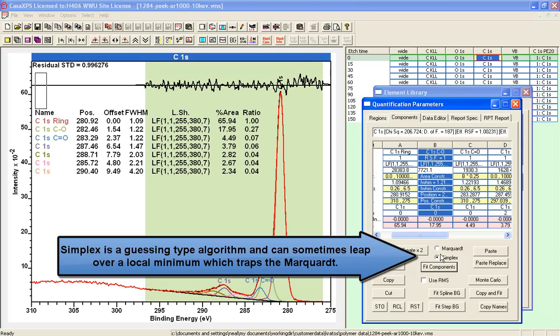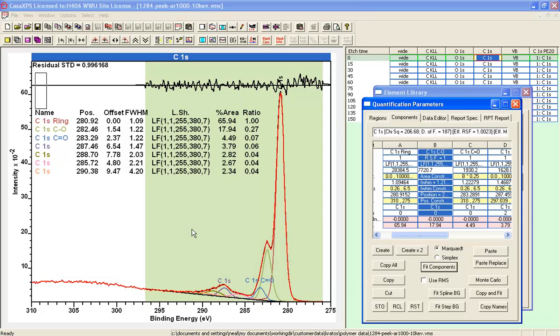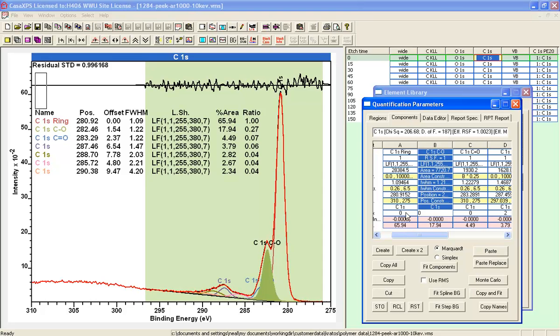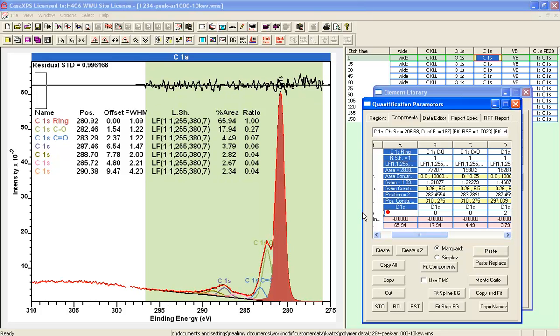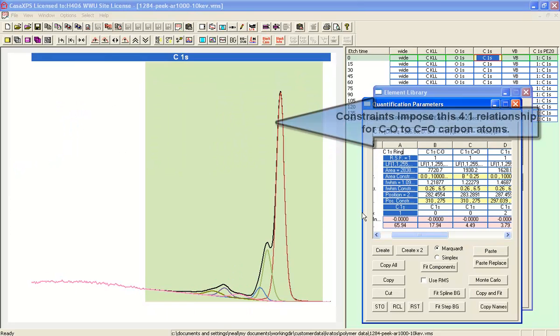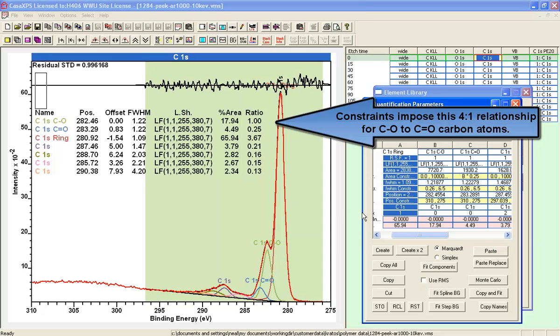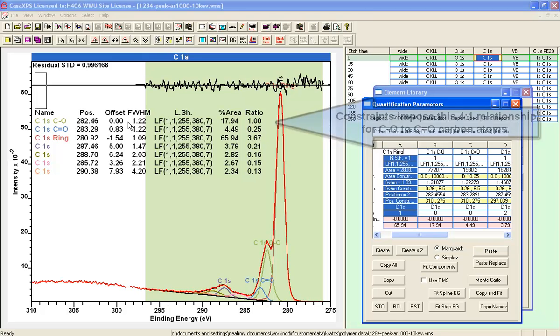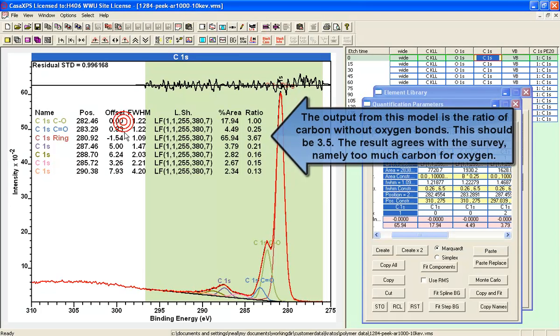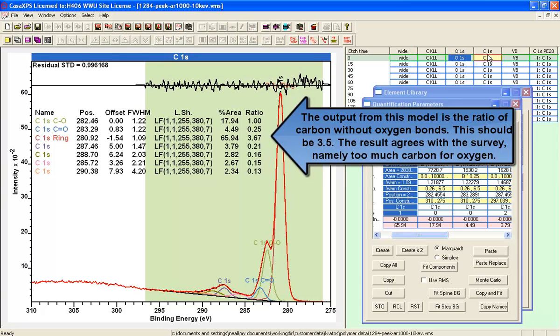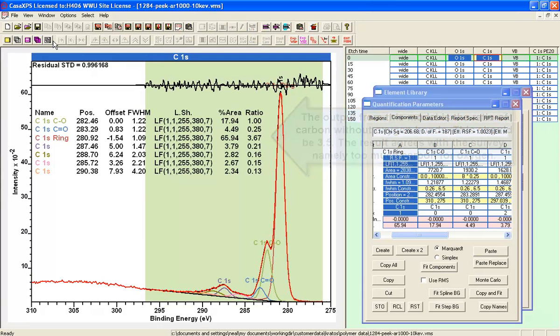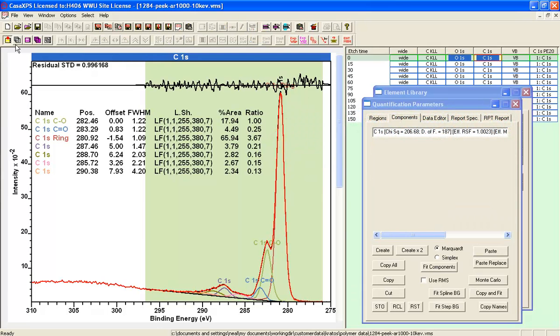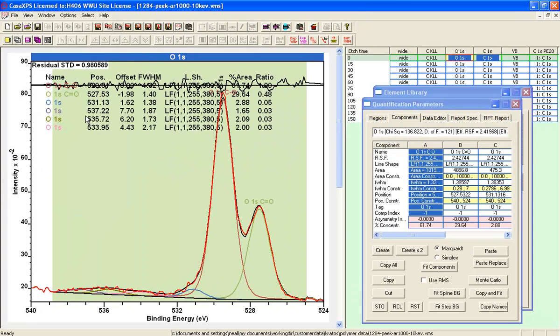What we'd like to see is how many carbon atoms we think are within the ring structure compared to the singly bonded carbon. There ought to be 14 within the ring structure not bonded to oxygen compared to four that are. So we should expect to see a ratio of 3.5 for the carbon within the ring compared to the singly bonded oxygen carbon peak. That's about what we see, a little bit more carbon than you might expect, but that's consistent with the survey spectrum.